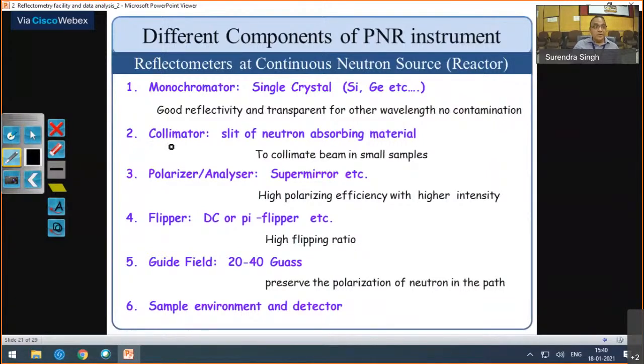Another component is the collimator. A collimator is used to stop the divergence of the neutron beam, because you have to put that neutron beam on the sample, and a collimated beam is required, otherwise it will deflect from the sample, I mean from all over, and then you won't have a well-defined beam of neutrons to do the reflectivity. So in any experiment we need a collimator, and this is nothing but a neutron-absorbing material with a sharp opening made in it, so that the neutron passes through while others are absorbed by the surrounding material.